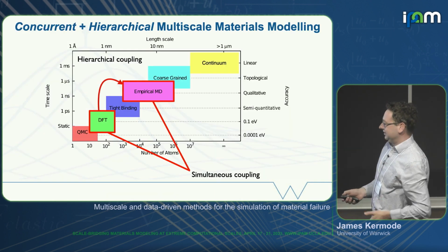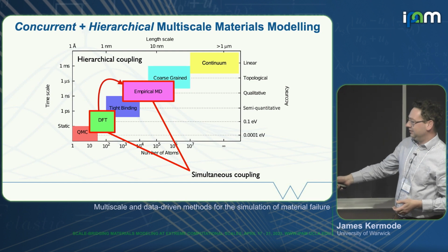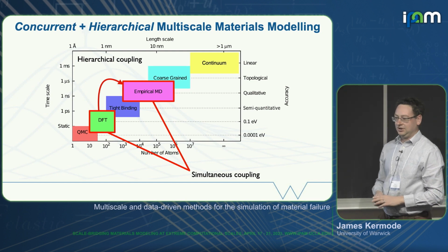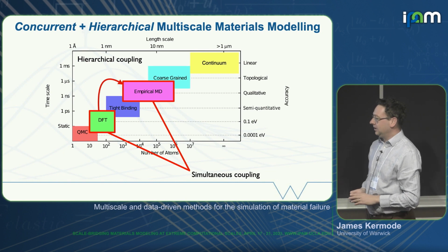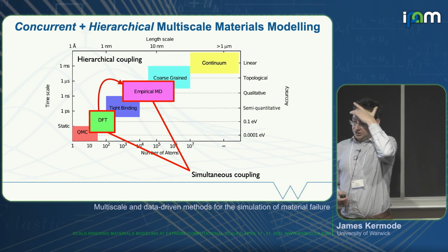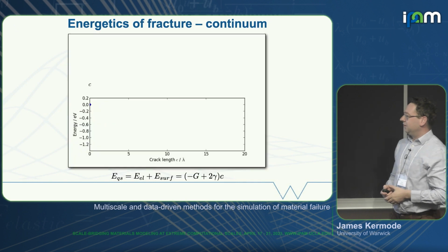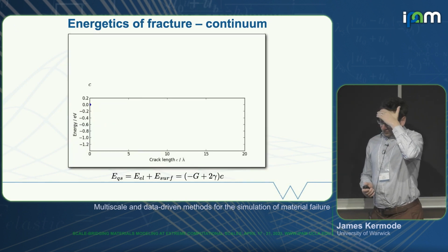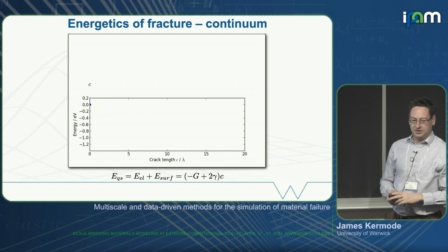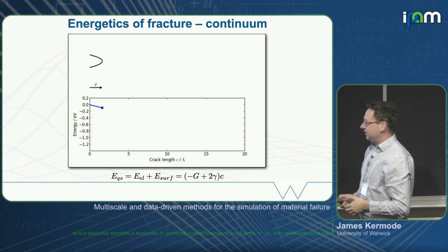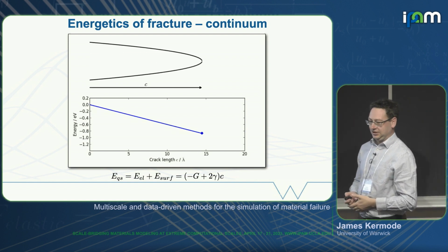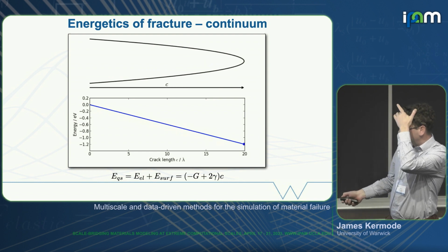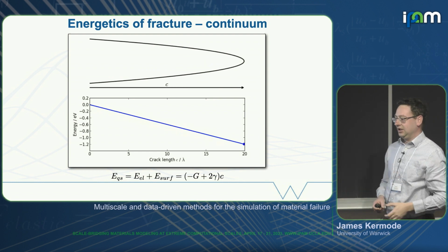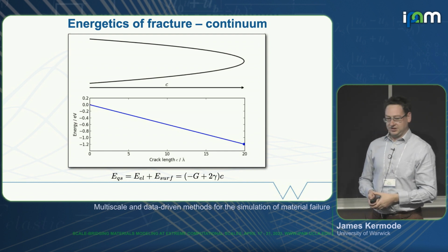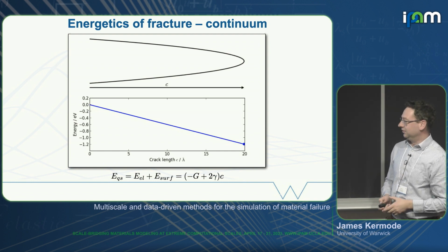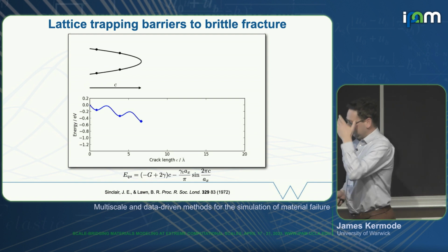Okay, so that's actually quite a nice example of combining some simultaneous coupling in order to bootstrap an improved hierarchically improved model. Now I want to come back to fracture for the last example on this concurrent coupling. So just a kind of brief review of the energetics of fracture for those who are a bit less familiar with it. In a continuum setting, cracks propagate because it's energetically favorable to do so. So because the cost of opening surfaces is less than the strain energy release associated with unloading the material. When we put atoms into the picture, things are a little bit more complicated.